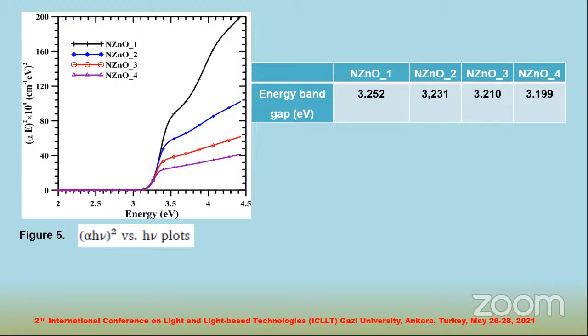The optical energy band gap of the film decreased from 3.252 electron volts to 3.199 electron volts as the thickness increased from 250 nanometers to 550 nanometers. The corresponding values of the band gap have been given in a table.